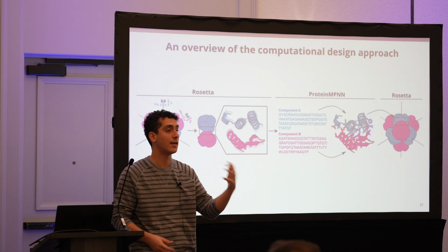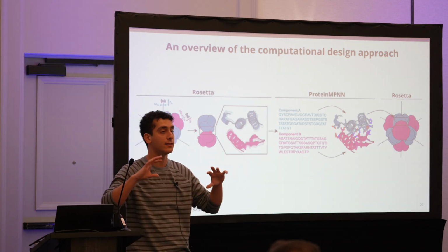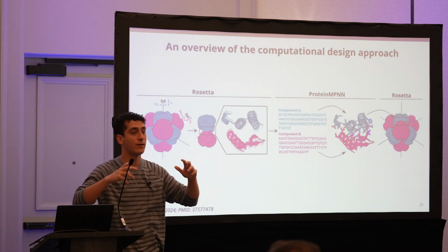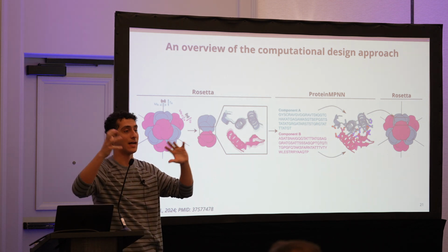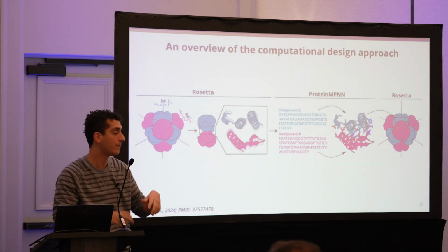So if I want a tetrahedral, an octahedral, an icosahedral, you tell it the architecture, and it's going to sample that space. It samples the space, and it wiggles. Usually you have 2 main degrees of freedom per component. You have your radial degree of freedom, so can you move it in or out? And then you have your rotational degree of freedom, so that's how you're rotating that component. Those are the 2 things that I call wiggling, basically. You're just sampling that space, seeing where these pieces can fit nicely together.